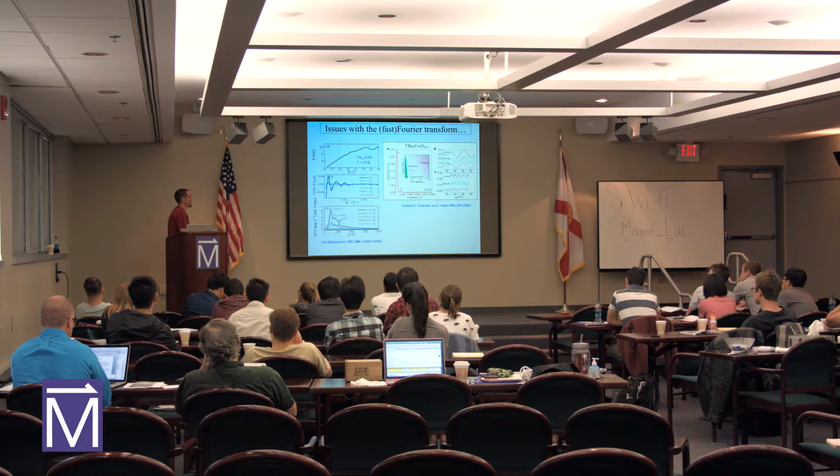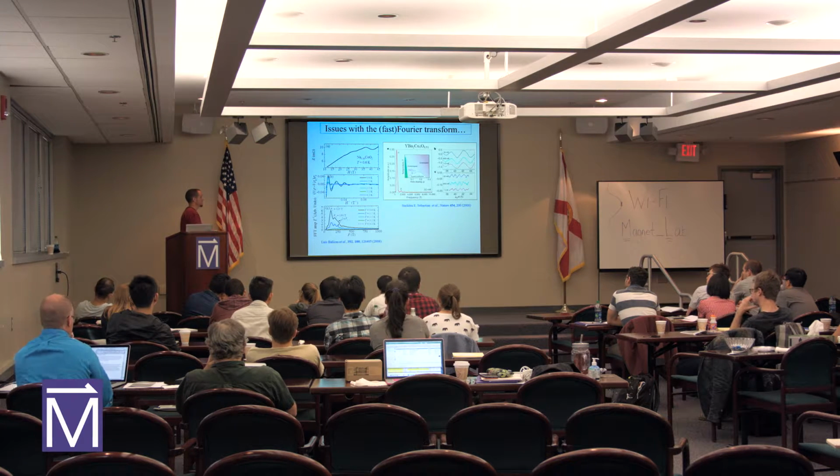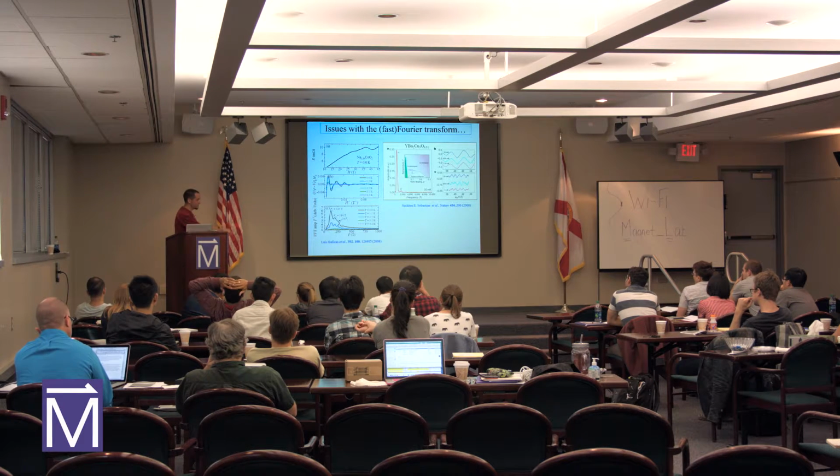So you can use a fast Fourier transform. But when you have small frequencies or very few oscillations, then the peaks from the fast Fourier transform kind of bleed together. It's hard to separate them out and compare their amplitudes. Again, for this study, they were able to complete it. But one approach to this would be to just try to improve your technique. Maybe you can see the oscillations down to lower fields. The more oscillations you see, the easier it is to analyze. But you can't always do that. Sometimes unique problems come up.